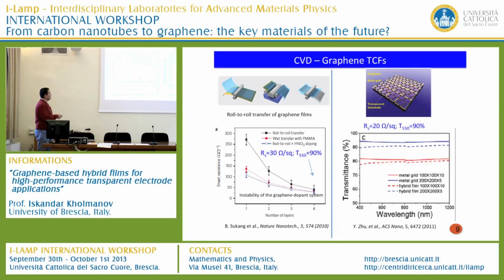And this group has used nitric acid in order to dope the graphene, but the problem here is the nitric acid is not stable, so the sheet resistance may increase about 50% within a few days. Another approach was proposed by the Rice University group, who transferred graphene on top of metal grids produced by lithography technique, and improved the electrical conductivity. So the sheet resistance is lower in this case. So here is single layer graphene, but the electrical conductivity here mainly comes from the metal grid rather than graphene.